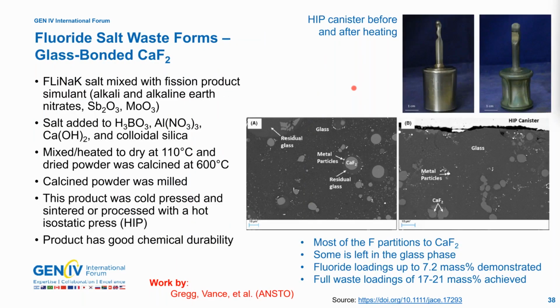So as I mentioned, very few studies have been done looking at fluoride waste forms. This is a study done at ANSTO, by Dan Gregg and Lou Vance before he passed away. This is one of his last projects that he worked on. It's a really neat process that they developed where they took a FLiNaK salt mixed with different fission products. The simulant was alkali and alkaline earth nitrates as well as antimony and moly oxides. These salts were added to boric acid, aluminum nitrate, calcium hydroxide, and colloidal silica. They were mixed, heated, and dried. They were calcined.